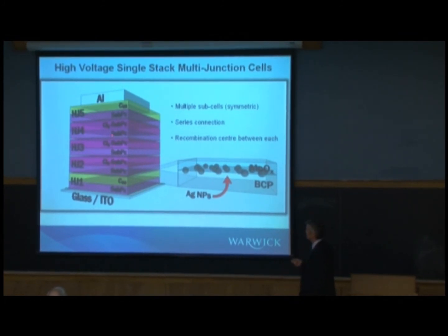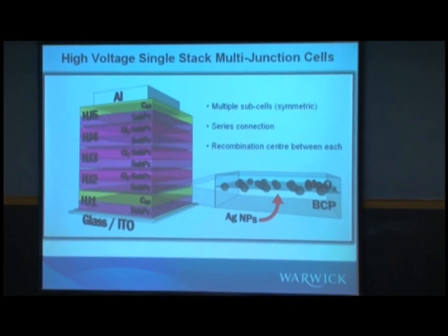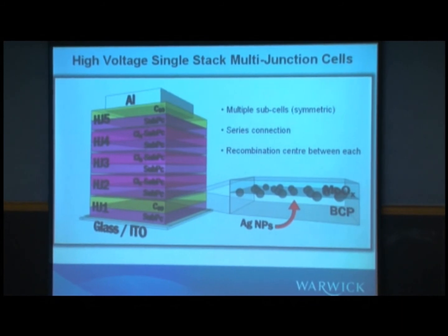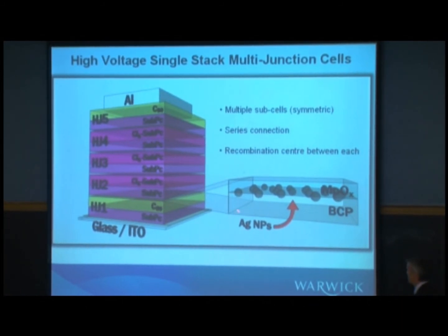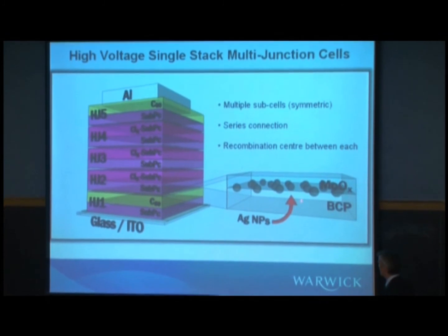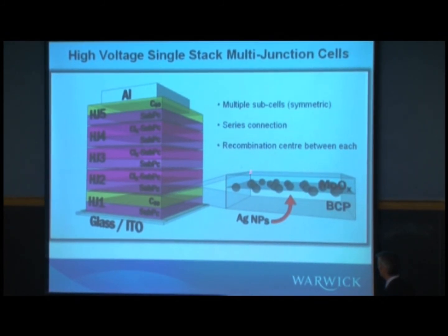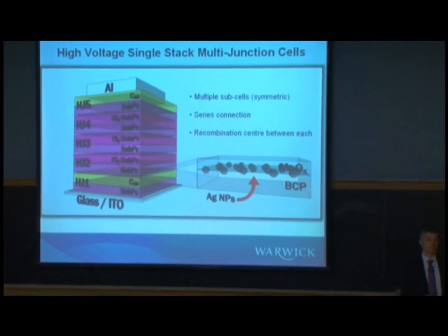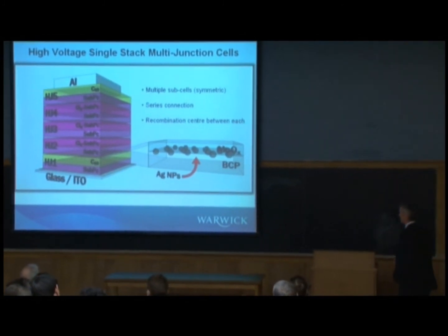They're based on the same materials, subphthalocyanine, Cl6 subphthalocyanine, so they're basically absorbing in the same region. And we're stacking very, very thin layers on top of one another, each one with a recombination zone based around silver nanoparticles, BCP, and molybdenum oxide in each particular case.